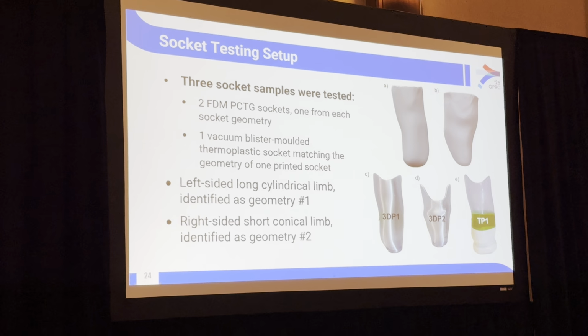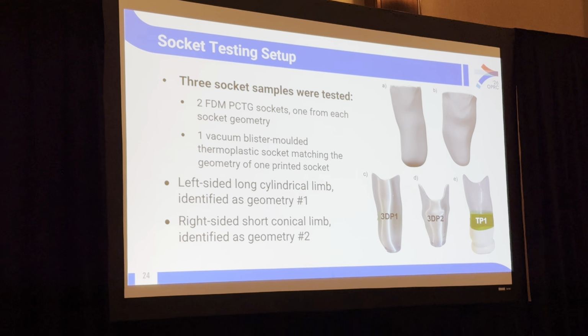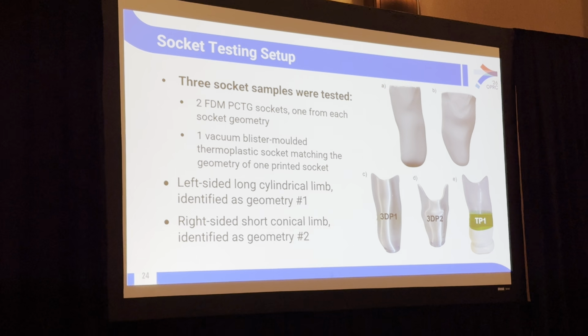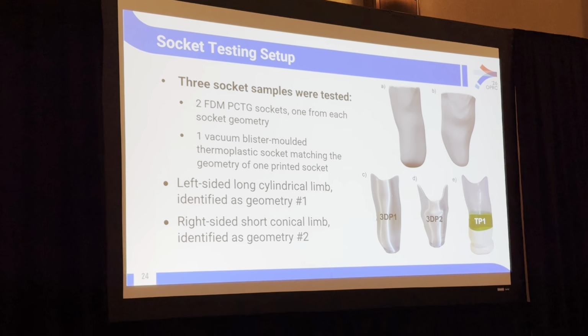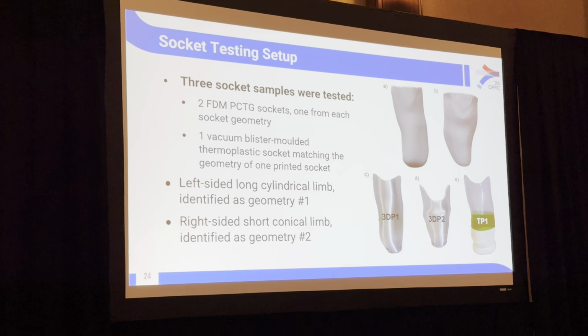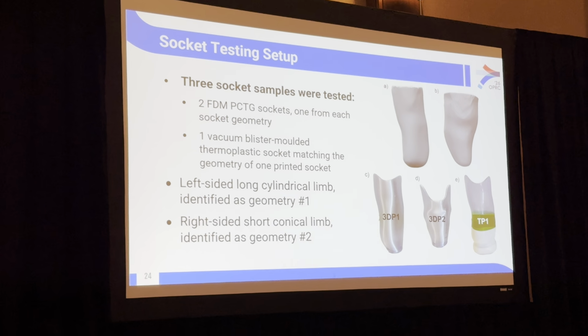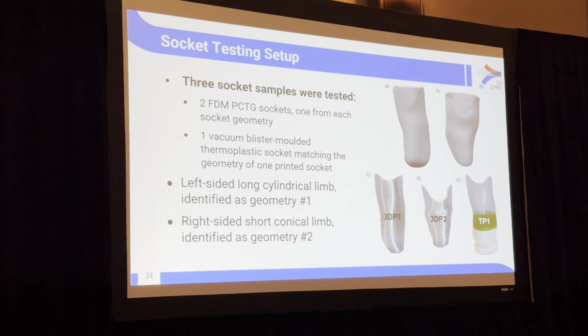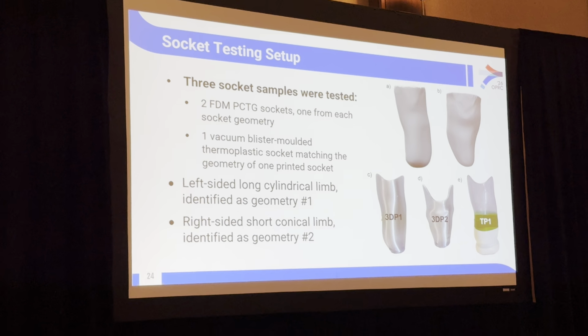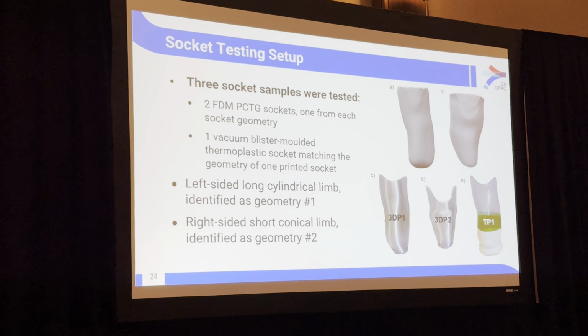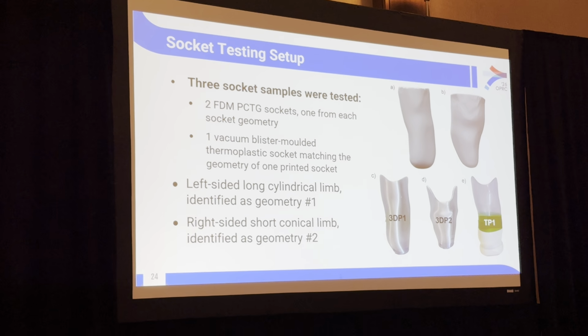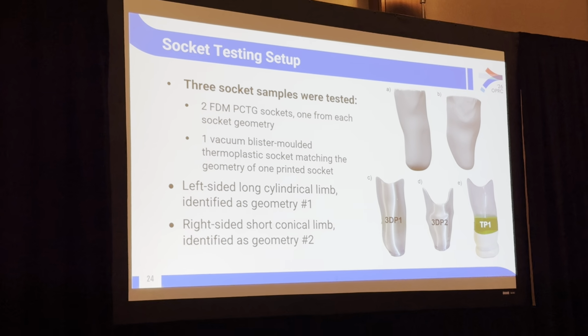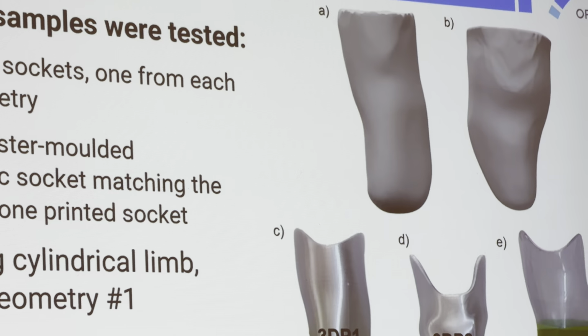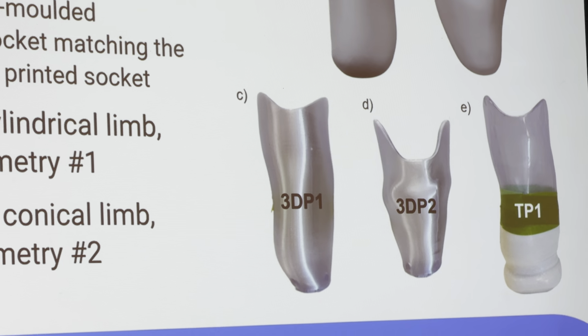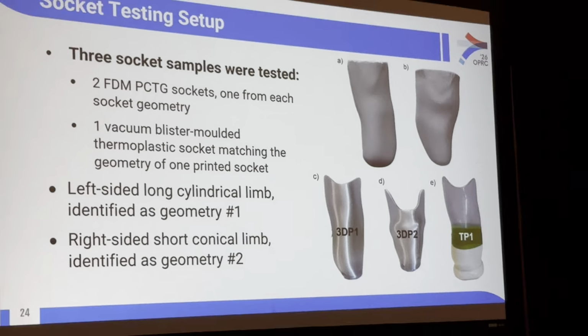For our socket testing, we performed our testing on 3 socket samples, 2 of which were FDM 3D printed, 1 of which was a blister molded thermoplastic socket. This allowed us to compare results across fabrication methods, but we also tested across different shapes of residual limbs. So we tested a longer, more cylindrical limb, which we identified as geometry number 1, and a more shorter conical limb identified as geometry number 2. And so you see here, and I'll reference them a little bit throughout our results, they were identified by their geometry and their fabrication methods. So we have sample 3DP1, 3DP2, and TP1.